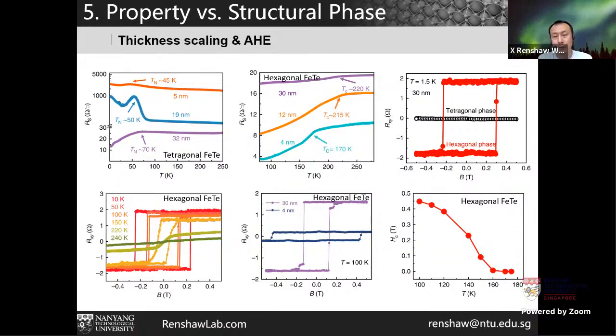When we sweep the magnetic field, I see that the tetragonal antiferromagnetic phase, the black curve, gives us a flat line, and the ferromagnetic hexagonal phase gives us a very nice anomalous Hall effect or hysteresis loop. So from the loop, we can clearly identify, or confirm, that the hexagonal phase is ferromagnetic. We can also very reliably characterize its coercivity as a function of the temperature.